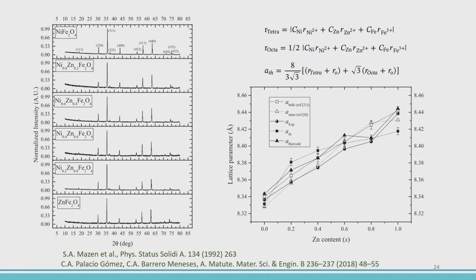This is important: how you start, assuming this. We have here the concentration of nickel in the tetrahedral site, and this is the radius of the nickel at the tetrahedral site, assuming high spin and also the 2+ oxidation state. The same for zinc and for iron at the tetrahedral and also for the octahedral.